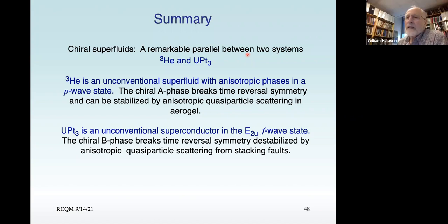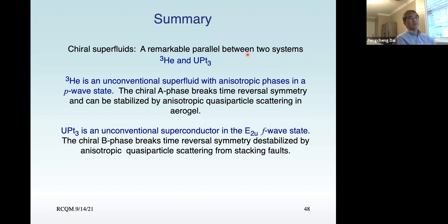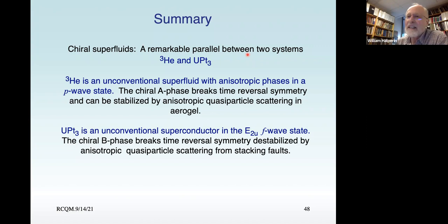Well, you grow the aerogel in a cylindrical glass tube, and then you use a plunger which has the same symmetry exactly, and the Poisson ratio is non-zero, but it's not free. Now, when you take a picture, we do optical birefringence. You get an image of the entire thing, and it's quite homogeneous. You can therefore see from the light intensity in the photograph how uniform it is.